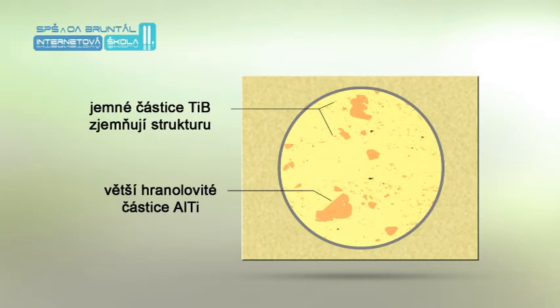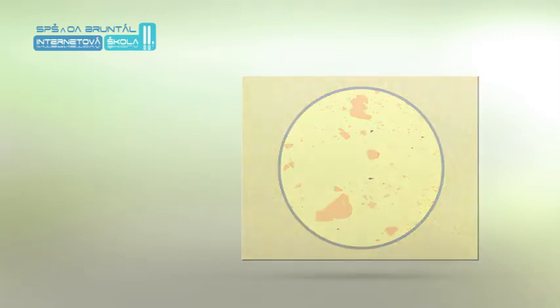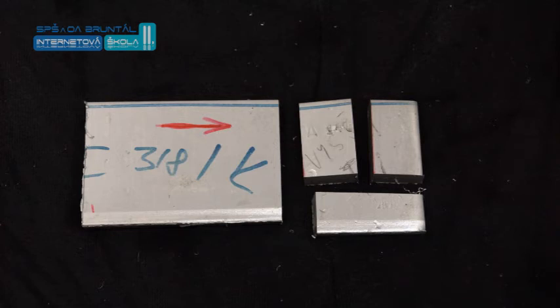The most important measure to prevent formation of these inclusions is choosing a suitable grain refinement agent with minimal borides. Borides are feared and dangerous inclusions due to their hardness, can lead to foil porosity, tool wear, and deposition on extrusion tools and subsequently grooves on the extrusion surface.